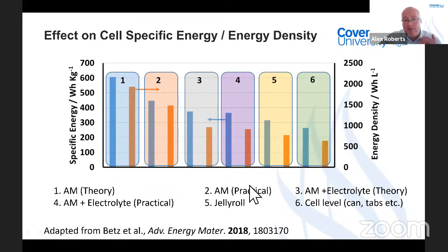If you then add in the mass and volume of electrolyte you're going to need, in theory and then in practice, we see another drop. You add the components of the jelly roll, such as the separator and the current collector, and we get a drop again. Then when you get to case number six, we put in all of the mass and volume of the can or pouch material or tabs and everything else that goes in there to get the numbers and values that our end user is really looking for. And as you can see, these are significantly lower than what we thought from the initial work.